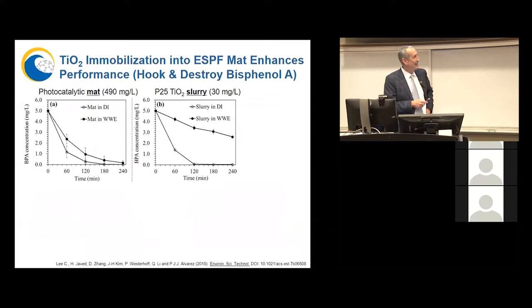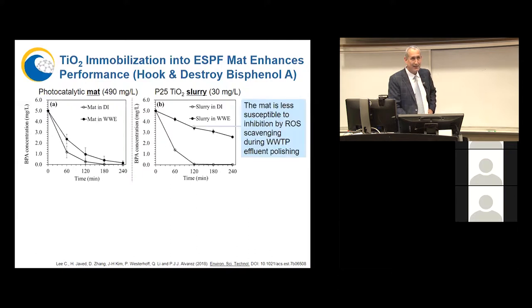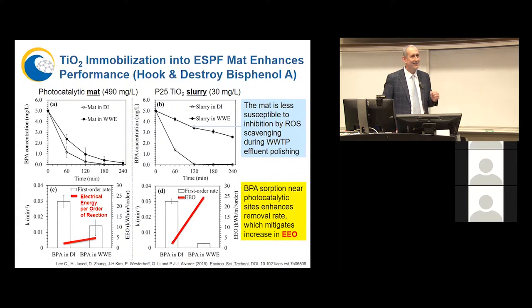And what I want to point out is that in both cases, there is a significant loss in performance as you move from an ideal system with distilled water to real wastewater effluent where you have a lot of ROS scavengers. But that decrease in performance is much less for the photocatalytic mat because it's able to bait and hook the BPA close to the photocatalytic site so that the ROS are more efficiently utilized. And this more efficient utilization results in significant energy savings. And this is what is more important here. Because the capital expenditure for photocatalysis are nothing compared to the operation expenses, and most of it is energy.